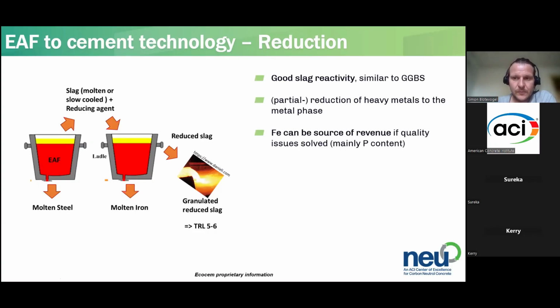One advantage of this is that the molten iron you get out of here, if you condition your process correctly, could be re-injected to the steelmaking process given you reach a certain purity. And that's a real concern, because if you reduce all the iron out of the slag, you will reduce also the phosphorus out, and that wouldn't be good for the steelmaking process. So likely you can't go to full reduction for chemical reasons, and there may be a compromise to be found.